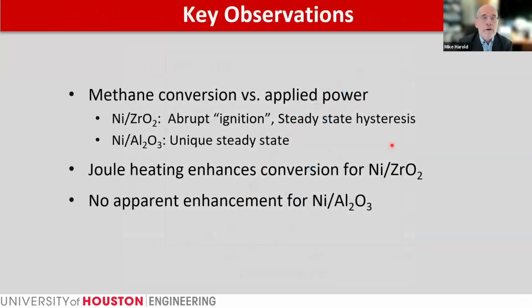So let me stop here and recap the data that I've shown you. First of all, the methane conversion versus applied power for nickel zirconia exhibits an abrupt ignition and steady state hysteresis of methane conversion versus power and wire temperature. On the other hand, nickel alumina shows a more conventional unique steady state. Furthermore, the Joule heating for nickel zirconia enhances the methane conversion over a range of power settings, but there's no apparent enhancement for nickel alumina.